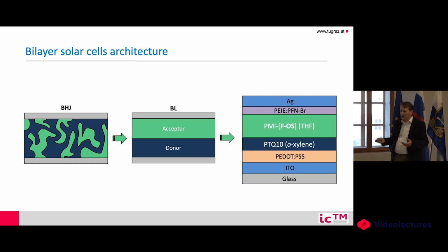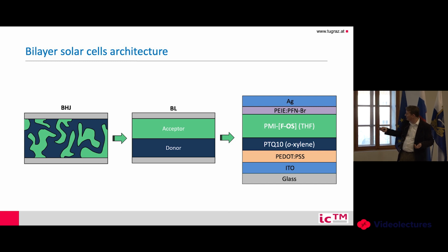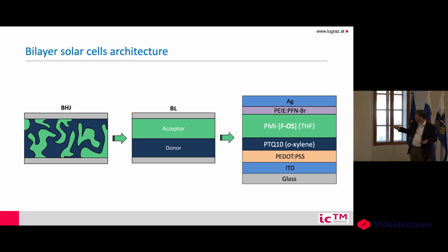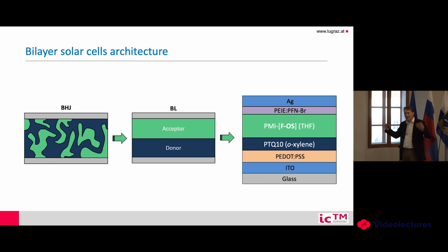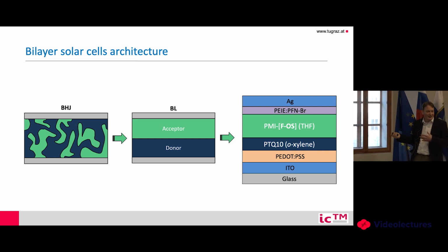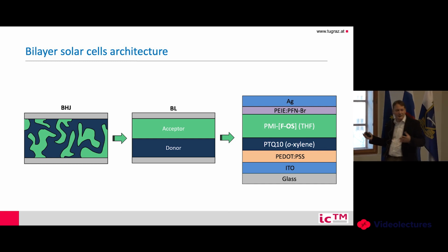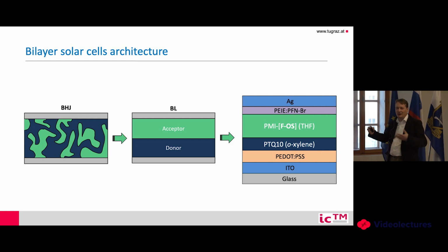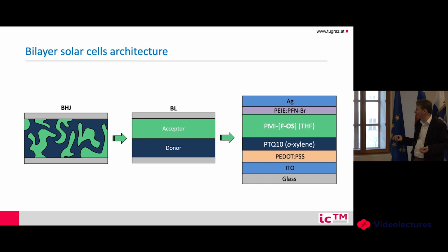Then, of course, you have to optimize your solar cell. You build up your solar cell on a glass substrate, which is covered by a transparent electrode. Then you have a selective contact, and then you have your active layer. Then you have your interface layer, and then you have the back electrode. So it's not only the material, you have to optimize every single step. This optimization of the solar cell also takes a long time, so you have to invest a long time here.